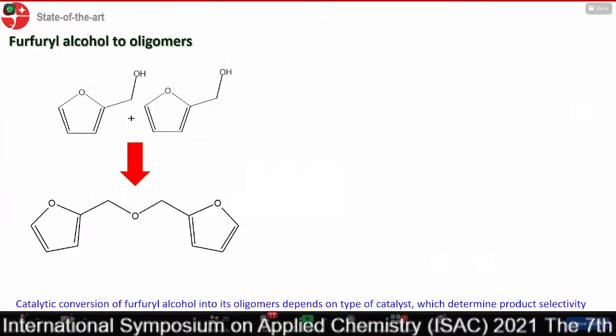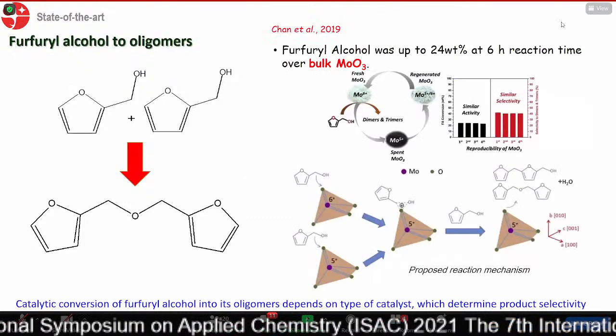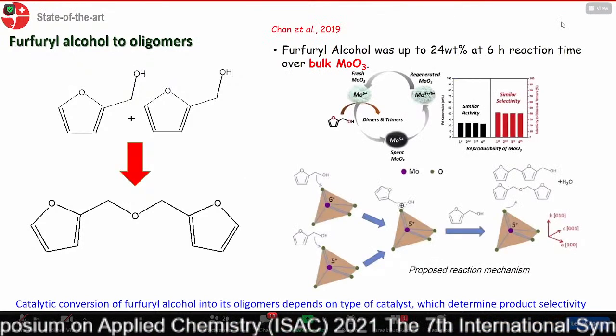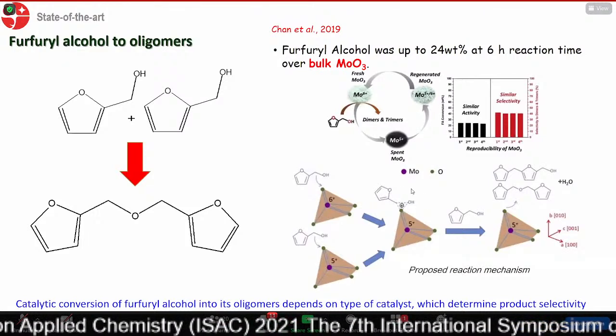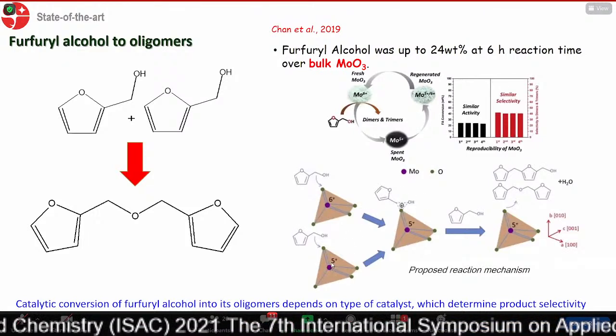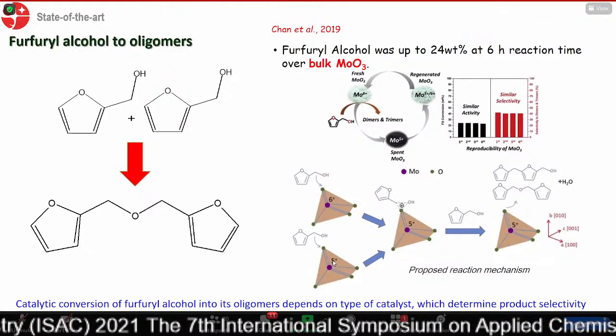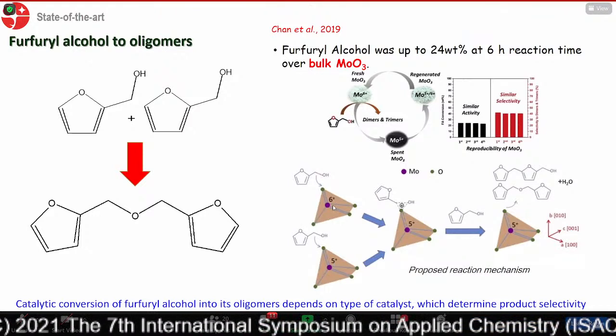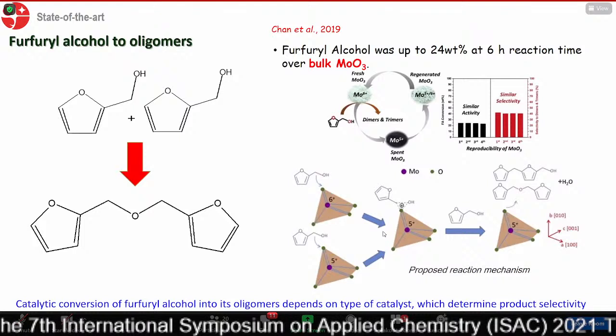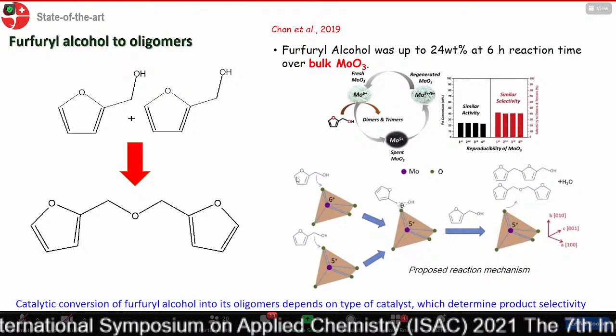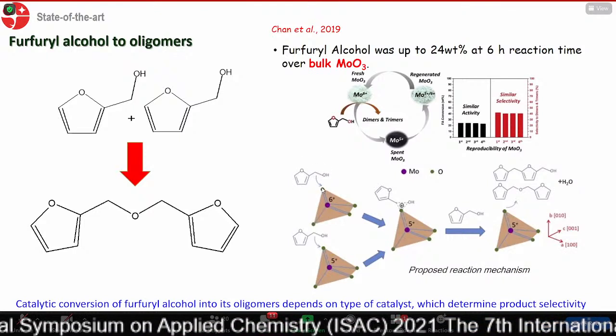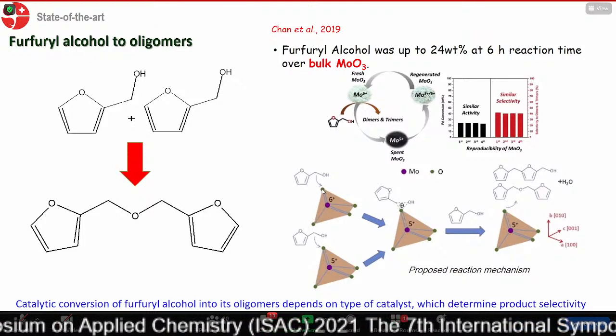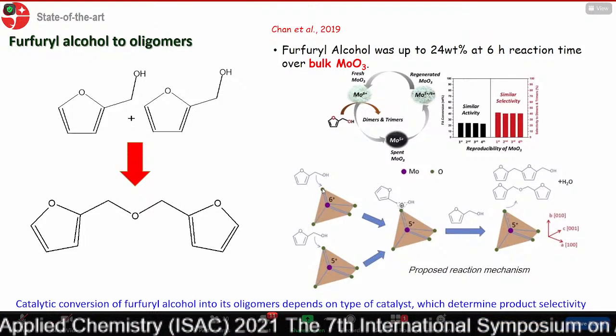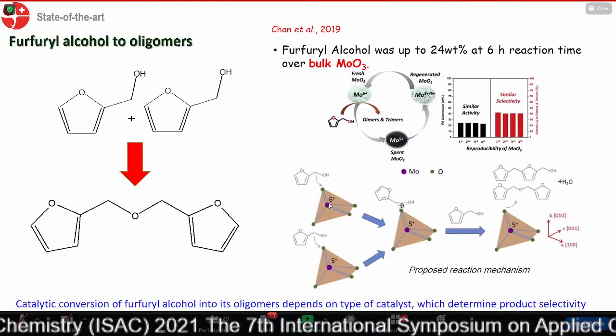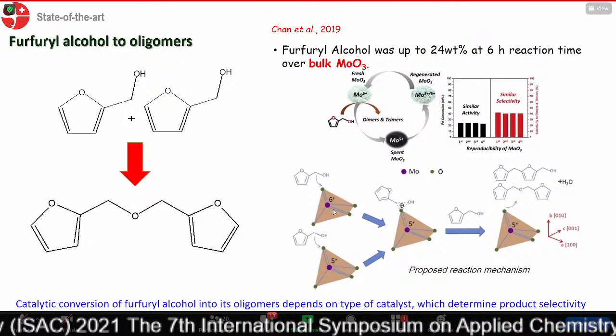So why is this molybdenum oxide active for the reaction? Since it has these two different valences, 5+ and 6+, and both of them are active during the reaction. So this furfuryl alcohol is connected with this oxygen bond on the edge of this structure of molybdenum. So that's why this molybdenum oxide is active during the reaction.